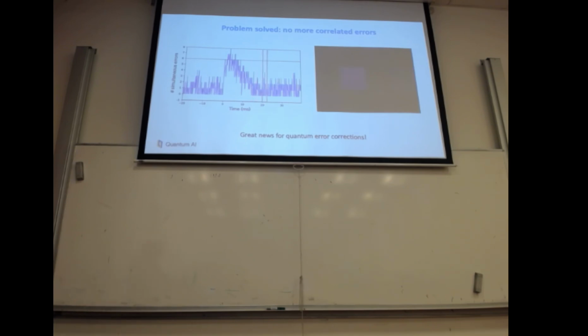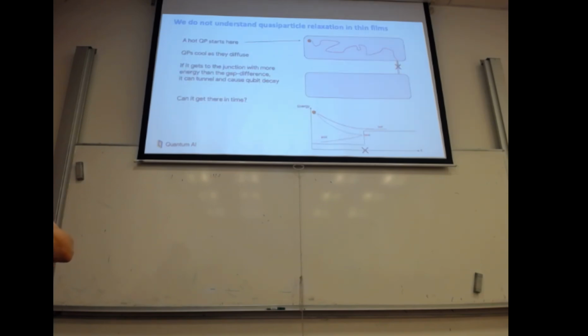But now comes the big question that was raised by Martinez, that this experiment works well from a theoretical point of view because we might understand that close to the junction, the quasi-particles are cold, so it's clear that they don't get enough energy to be excited and then tunnel. But, and that was the main question, suppose that you have a high energy quasi-particle that is created somewhere in the paddle. The crucial question is, this has very high energy, it's very hot. How fast does it diffuse? And can it get close to the junction? Because if it gets close to the junction and still has this high energy, then it can pass through.